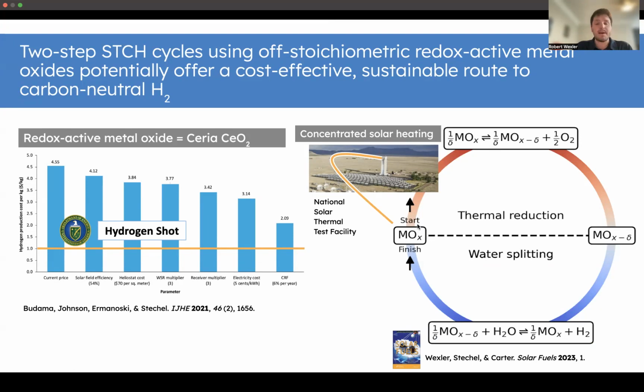The main idea behind two-step STCH with redox-active metal oxides is that we take a metal oxide and heat it to temperatures around 1350 C. Those are the conditions that we've used, using concentrated solar heat. In practice, this would mean putting it on sun somewhere like the National Solar Thermal Test Facility. This leads to reduction of the metal oxide through the formation of oxygen vacancies and the production of oxygen gas. And then the material is cooled to about 850 C.